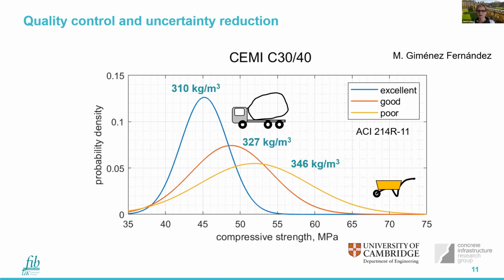So if we were to test multiple concrete specimens with each of those types of quality control, we'd see this sort of scatter. But what that means is that with higher quality control, we can have a lower cement content because we don't have such variability. And for this particular example, we could get away with 310 kilograms per cubic meter with excellent quality control, whereas with very poor quality control, we would need 346 kilograms per cubic meter. So there's a cement penalty for having poor quality control.